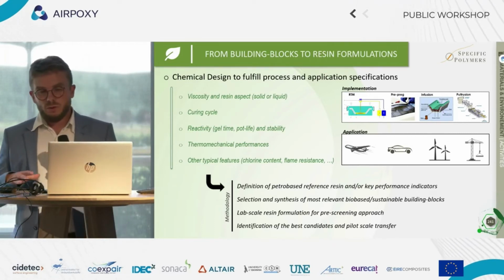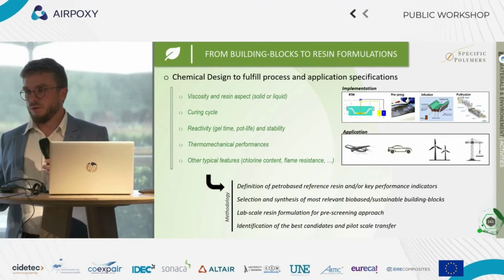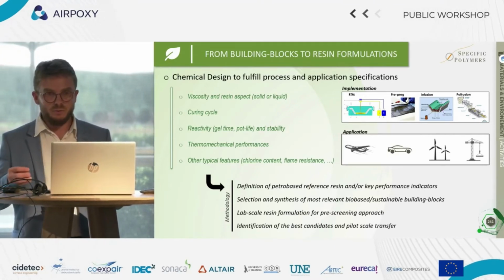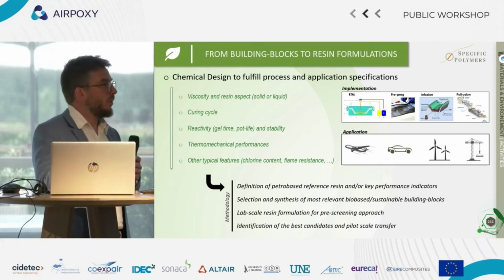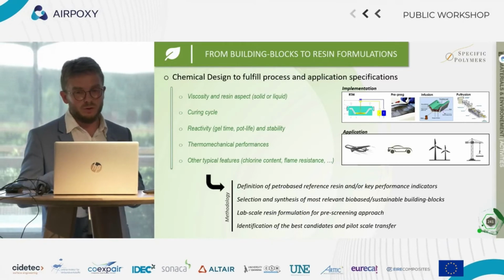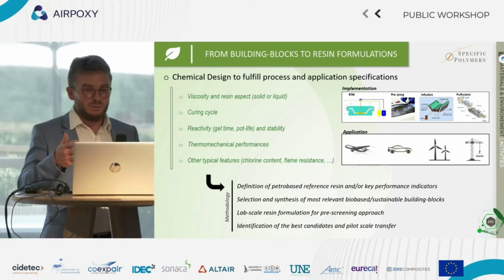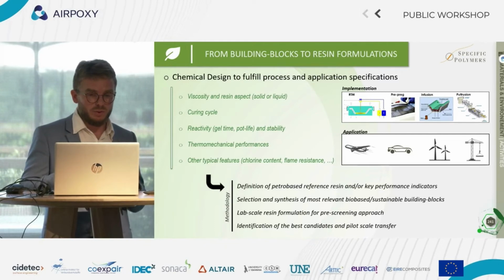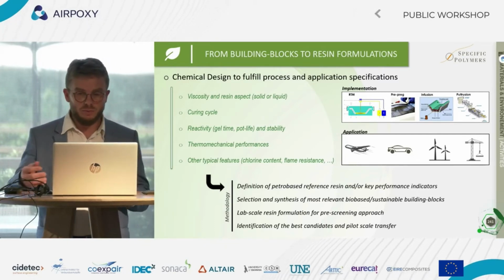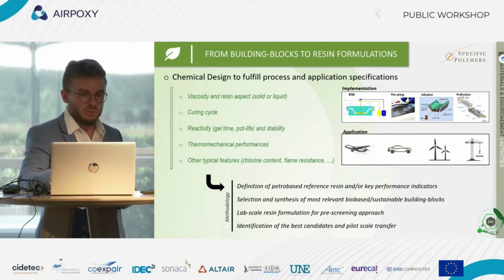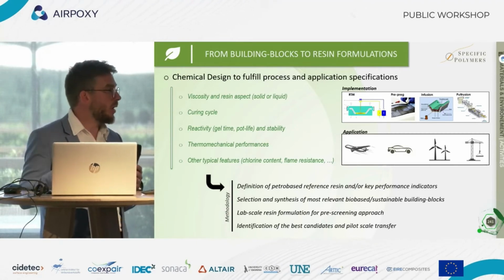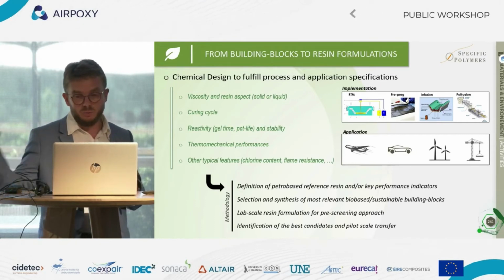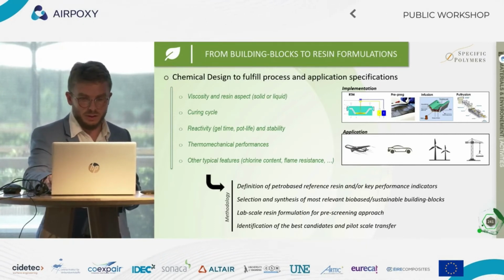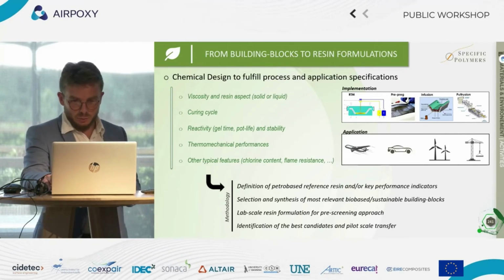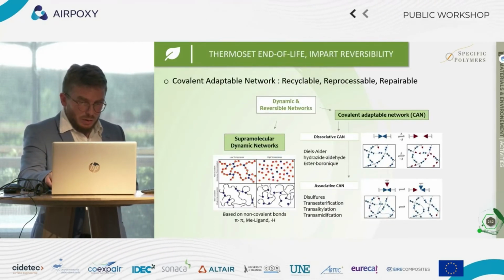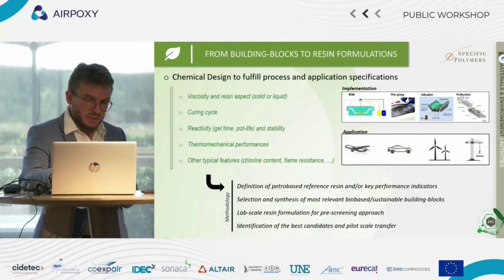So in terms of methodology, we always act the same. We want to define a petro-based resin that is a reference resin, which gives us the values that we need to target. We characterize this resin, and then we try with the bio-based or the sustainable alternative to make something that brings the same properties in terms of rheology or thermomechanical properties. We make the building blocks, we make the resin formulation, we make a pre-screening at lab scale, we evaluate the results, and then when we have the best candidate, we work on the pilot scale transfer and optimize the process to produce larger quantities. So this is basically the idea for the bio-based part.